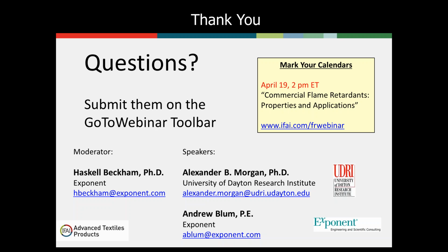Something like that, you can really stop before it ever happens because you've got everything running the way it should be. I do the same thing with vertical flame spread tests. I have a set of baseline material that I like to run before we run some tests, and we'll make sure that we're getting flame spread times, char lengths, things like that that are consistent for that material that I saw a year ago, 2 years ago, 5 years ago. So that's the key to making sure you're getting good, consistent test data: make sure the equipment is right and calibrated, and that you're doing some baseline testing to keep on top of it.